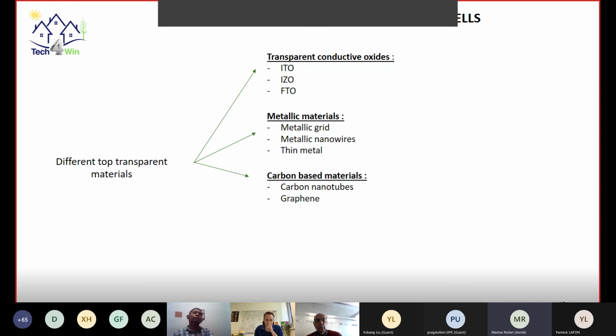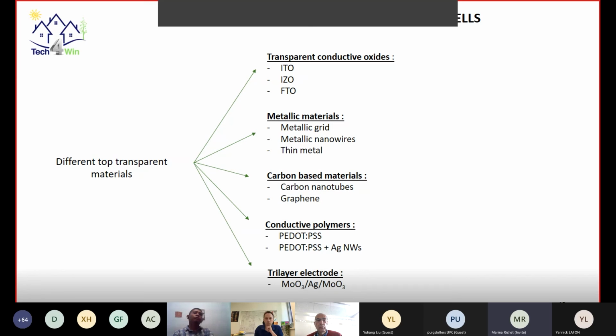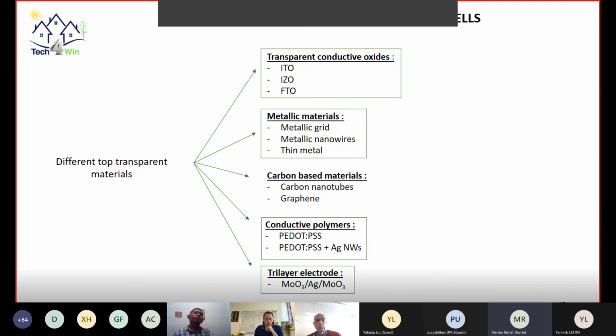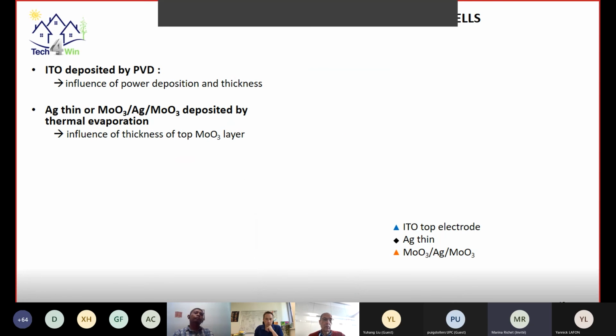In the literature, there exist different top transparent electrode materials such as conductive oxides, metallic materials, carbon-based materials, conductive polymers, and three-layer electrodes such as molybdenum oxide, silver, molybdenum oxide. In the project, we decided to work with four or five types of transparent electrodes. First, we worked with ITO deposited by PVD, and we looked at the influence of deposition power and thickness. The second one was the molybdenum oxide, silver, molybdenum oxide three-layer electrode deposited by thermal evaporation, and we looked at the influence of the thickness of the top MoO3 molybdenum oxide layer.